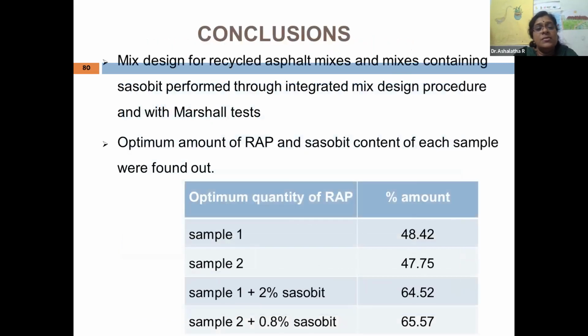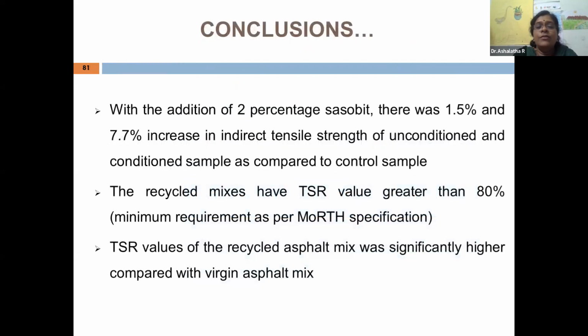And as a conclusion, we could say that the mixes designed for recycled asphalt pavement and mixes containing Sasobit, performed through the integrated mix design procedure with the Marshall test, and the optimum amount of RAP and Sasobit content for each sample were found out. And these are the values which we obtained. Of course, I told you that since it's the initial work, we are getting it on a higher side. With addition of 2% Sasobit, we found that there's a 1.5% and 7.7% increase in indirect tensile strength of unconditioned and conditioned samples as compared to the control sample.